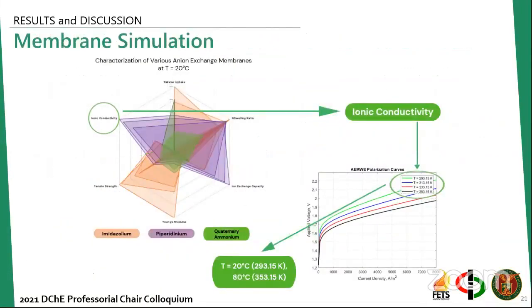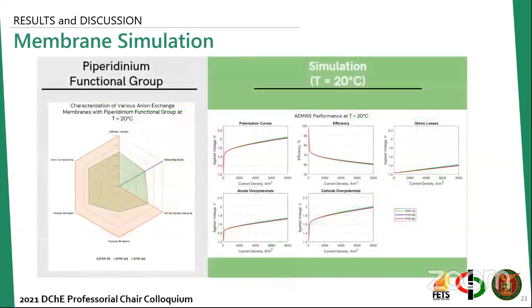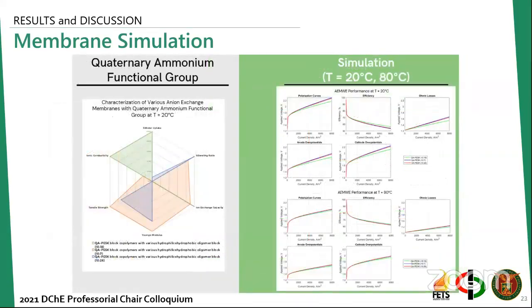For the membrane simulation, as mentioned earlier, the model only accounts for the ionic conductivity of the membrane. Thus, this is the only varied membrane property for the simulation to predict the performance of each membrane at the chosen operating temperatures. We look at the three functional groups. For the piperidinium functional group results, from the membrane evaluation chart, the PTP90, which is represented by the orange polygon, is expected to perform the best based on its properties. And this expectation was met when simulated, as shown on the performance plots to the right, represented by the red plot. However, we can see inconsistencies in the remaining two functional groups.